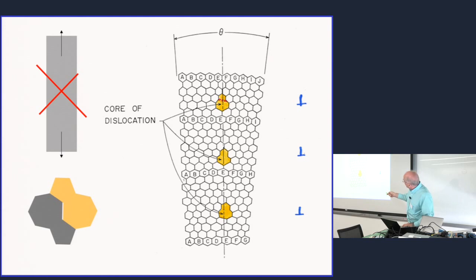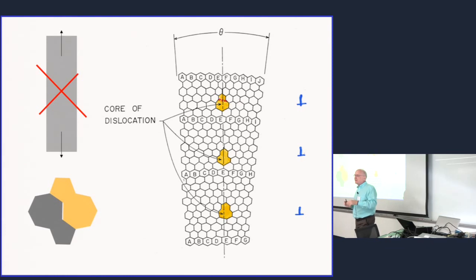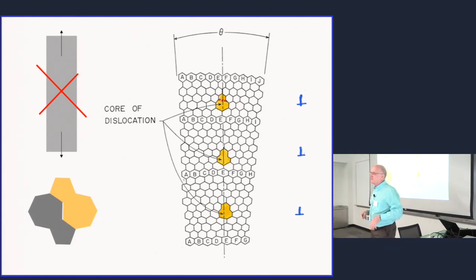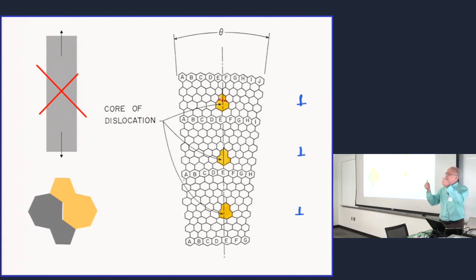Anyway, then you think, a nanotube is just a crystal. Now it's actually much easier because we know that graphene is a crystal, and so on. At that time it was almost a revolutionary idea because nanotubes were coming more from the chemistry world. And to say that it's a crystal was, okay, interesting, it is a crystal. And if a nanotube is a crystal, then we know how crystals and metals yield to very high tension. They yield to very high force by dislocation glide, by formation of dislocation loops and propagation through the lattice. And then you think something like this should maybe be happening in the nanotube under very high strain and some temperature.